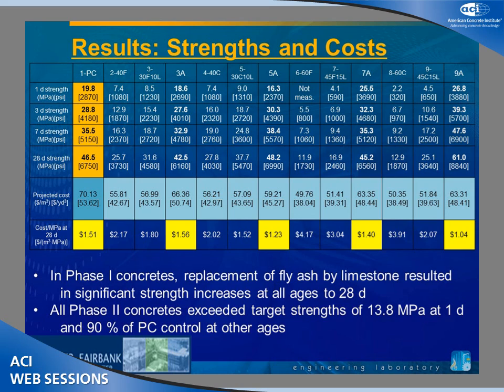And we wanted to be 90% of the controls at 3, 7, and 28 days as a minimum. And you can see the different mixtures that met or did not meet those criteria. Basically, we found that the Phase 2 concretes, the water-cement ratio reductions, or switching to the Type 3 cement were sufficient to meet the strength criteria.